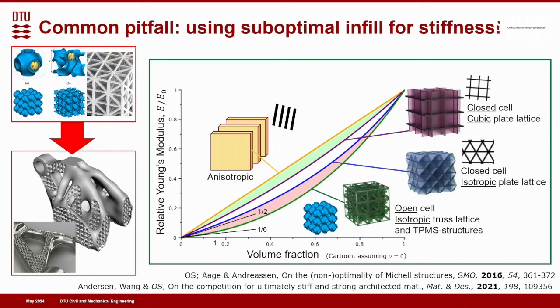But the more banana-shaped or the more curved the thing is, the lower stiffness you have. And if we are limiting ourselves to isotropic microstructures, then both the open cell isotropic lattice structure and the TPMS structures have an extremely low stiffness for lower densities. In fact, they have as low as 1/6 of the ideal stiffness. So if you already take into account in the beginning of your optimization process that you want to realize your structure with truss lattices or TPMS or other suboptimal microstructures, then the optimization will not give you any microstructure. It will say it's much better to do solid structures.